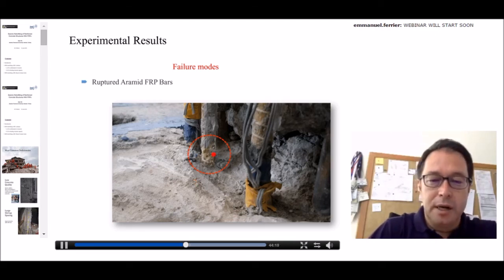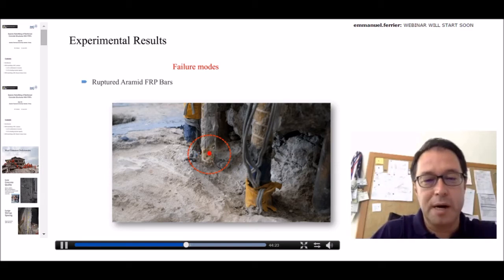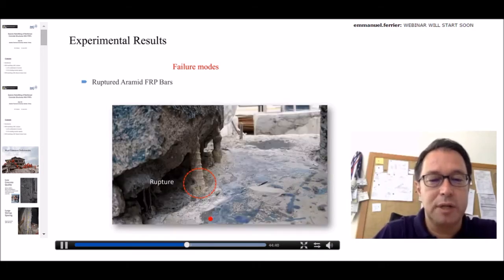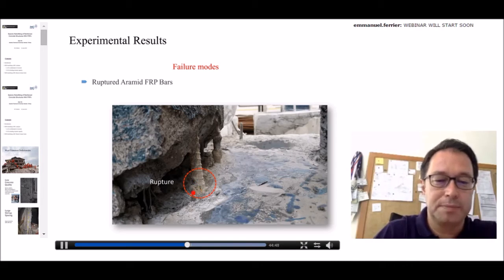Here you can see some ruptures of the FRP bars. This is something we don't like because the elongation capacity of these bars is not that high. But on the other hand, this fracture shows us that we have efficiently used these AFRP bars until their failure. So no debonding or other kinds of failures, which means that we can make use of the total capacity of AFRP bars.